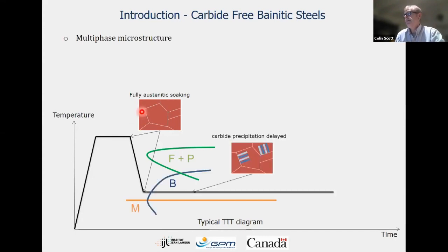Okay, then we have our isothermal hold. Now these steels have always got silicon in, so the austenite will decompose to bainite, essentially carbide-free bainite because of the silicon. So we should hopefully have no cementite or very little cementite involved.